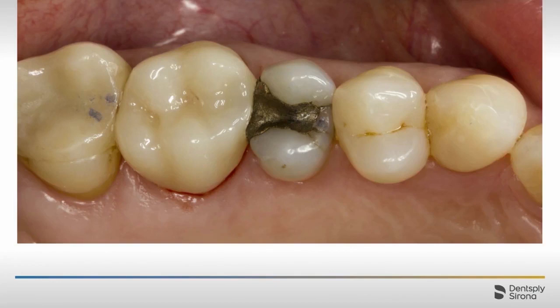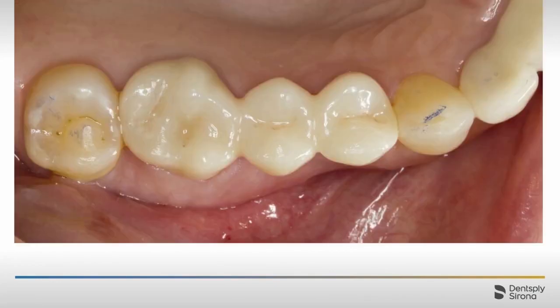They also have a bridge. So this bridge is a little bit higher value than I would have liked it. But again, this is a zirconia bridge fabricated in my office with an 18-minute and 39-second sintering cycle. So again, it's a little bit high value. I could have chosen a darker shade, but if we look at the overall translucence, if we can actually get around the fact that the value might be a little high, the shade might be a little bit bright, the translucence is looking a little bit more towards glass ceramic and a little less like traditional opaque zirconia.